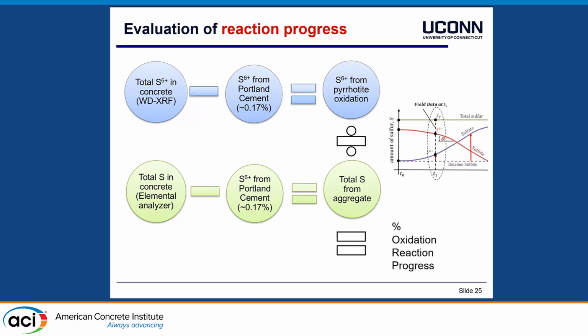So for example, if we have just one level of set in this time-dependent behavior from the field, you know the total sulfur from the concrete elemental analyzer, you subtract the baseline of the Portland cement, so then you get the total sulfur coming from the aggregate. So if you have the total sulfur here, subtract the baseline from sulfates, then you have this difference only from here to here.